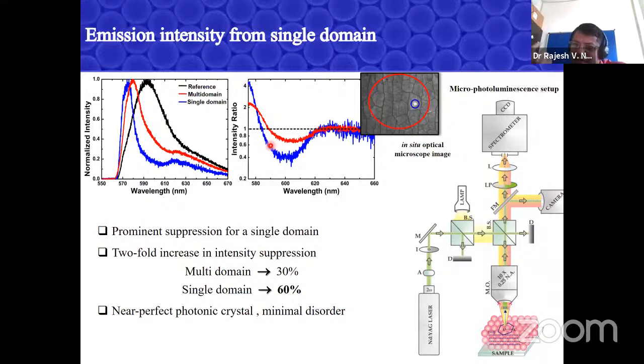So the contrast you get is usually around 0.6 or 0.59, but ideally you look for a system like 2 refractive index difference, which is not the case for us, because then we need electron beam lithography fabricated on silicon or gallium arsenide. So we were quite interested that yes, we could at least see a very huge change in emission intensity. So probably it will be nice to proceed further.